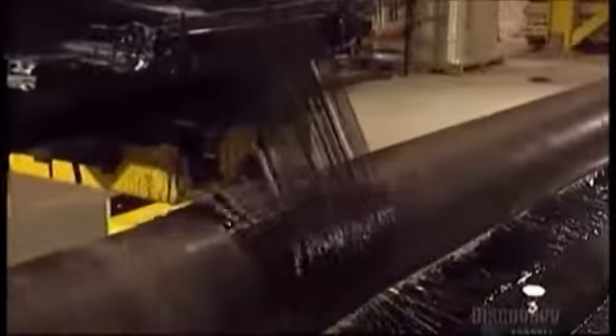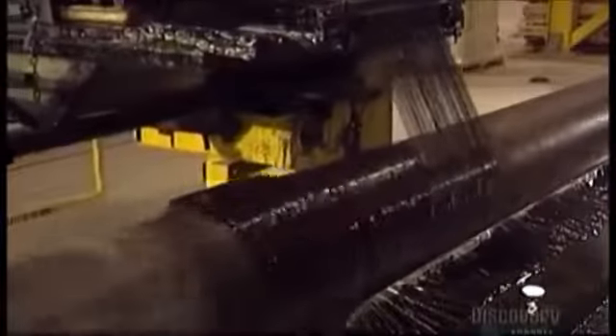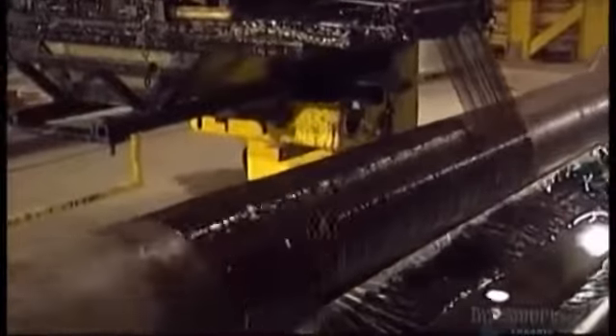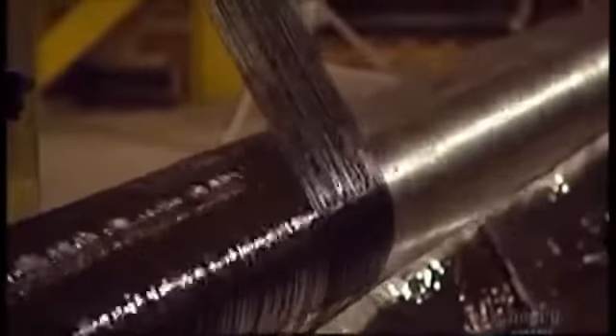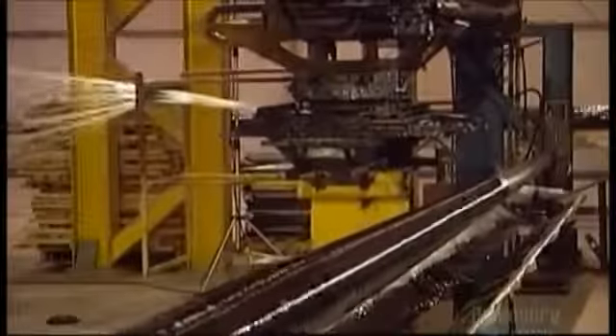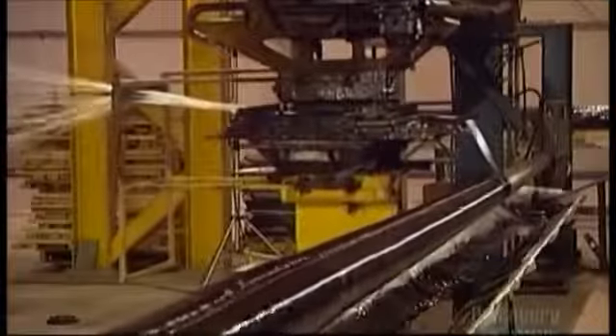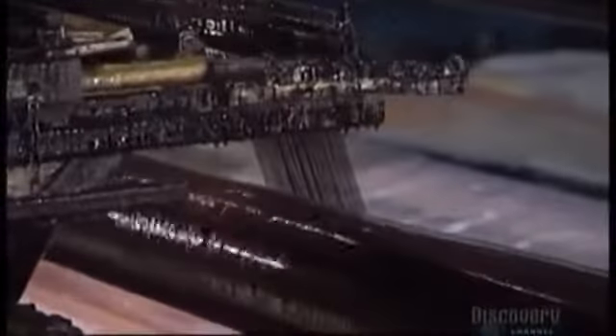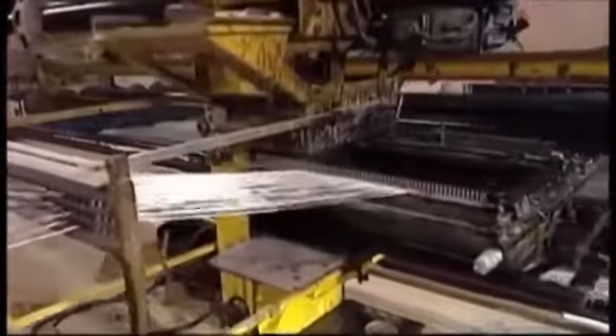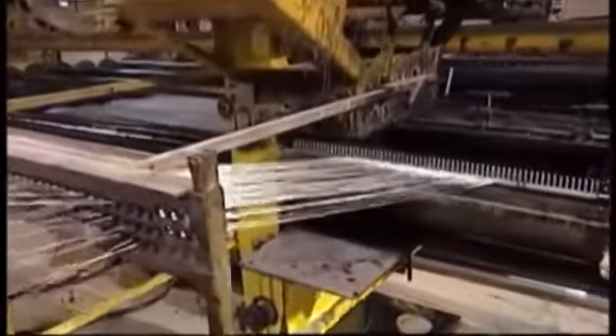Once the filaments come out of the bath, a machine called a filament winder wraps them around the rotating mandrel. The speed of rotation in relation to the speed of the winder is critical because it dictates the angle of the fibers. The lower the angle, the more that part of the pole will be able to withstand the wind and provide constant, stable lighting. When a pole bends in the wind, the light appears to flicker.